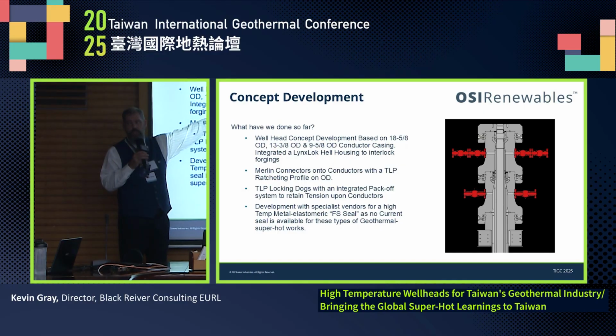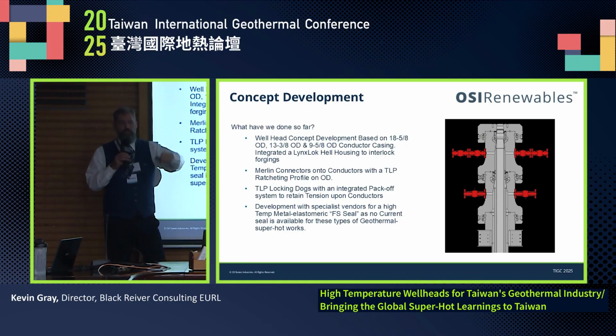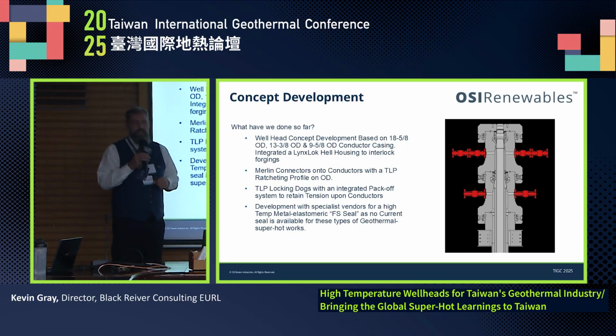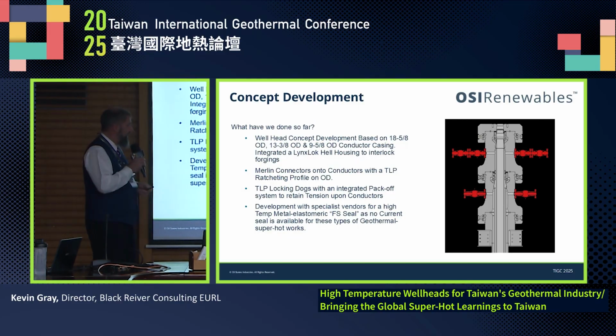We have already the technology to put the ratchet system in the wellhead, and the tooling is being developed so that once you have cemented, you put your wellhead on and the tooling will pre-tension your casing string. You don't have to maintain that tension in the casing string for the life of the well. We can come in and release that tension in stages. So if you're intending to go into a long period of maintenance shutdown for that well, what you would do is release the tension from the wellhead and allow that casing to contract without exceeding its tensile strength.